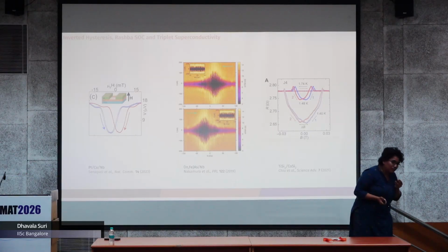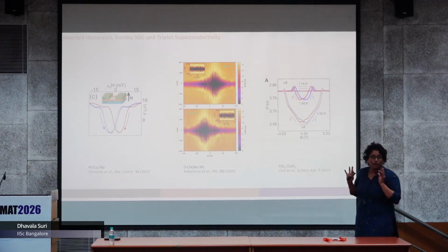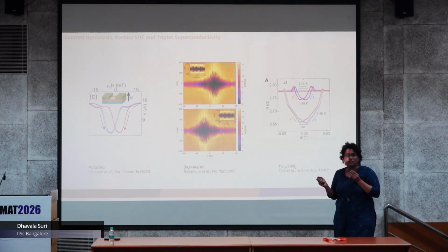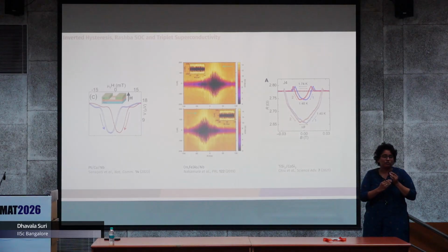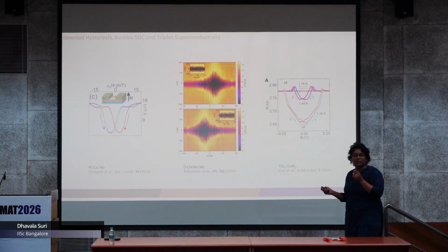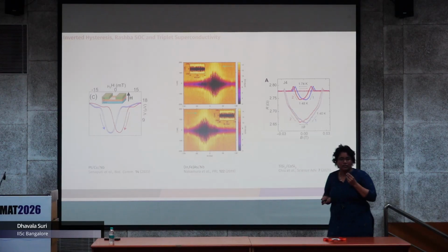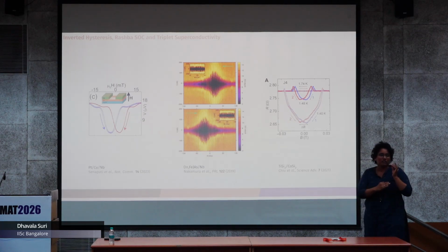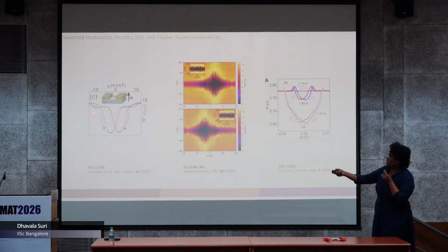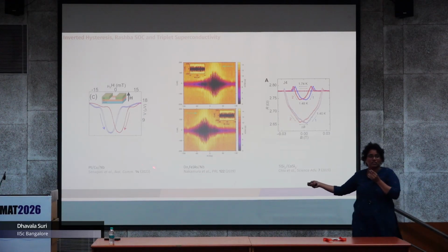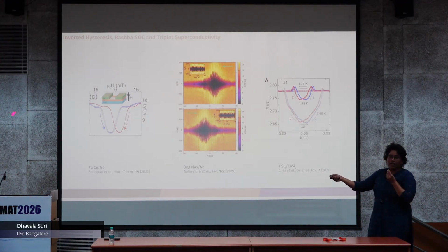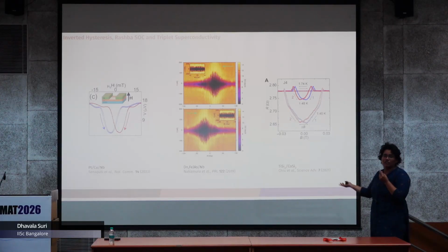And this kind of shift has been attributed to quite a few exotic things, beginning with phase batteries, spin triplet, and whatnot. If you look at literature, the moment there is some phase shift in the Josephson junction, it has been associated with really big names like spin triplet superconductivity, and so on. So obviously it doesn't really make sense just because you have a phase shift, that too in the wrong direction. If you see here, you come from the right, from the left. If you have the dip on the right, then it's a ferromagnetic hysteresis and you can associate it with triplet superconductivity. Whereas here you have the dip happening in the same direction even before crossing the field.